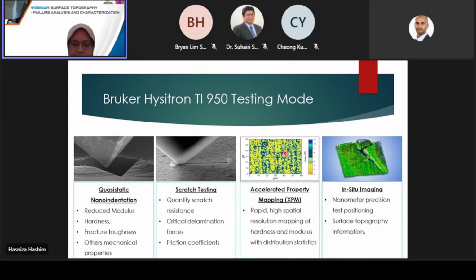we have indents over a 16 micron square area, and we assign a color map from low hardness to high hardness. In this case, yellow and orange represent the lower hardness, and blue represents the higher hardness. So you can get an idea of the distribution of hardness in your material. The system, as I mentioned before, is also equipped with in-situ imaging. It uses the indenter tip for nanometer-precision test positioning and surface topography information. In the following slide, I will show you the benefit of having in-situ imaging in our system.